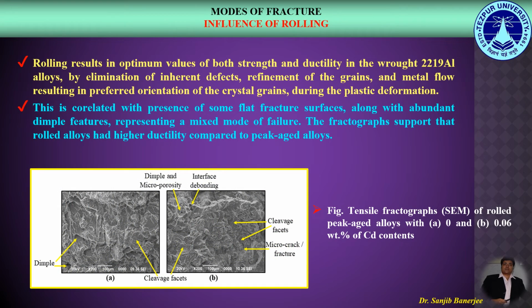While studying the influence of rolling, rolling results in optimum values of both strength and ductility. This is correlated with the presence of some flat fracture surfaces, as shown in these figures, along with abundant dimple features representing a mixed mode of failure. The fractographs support that rolled alloys had higher ductility compared to the peak aged alloys.